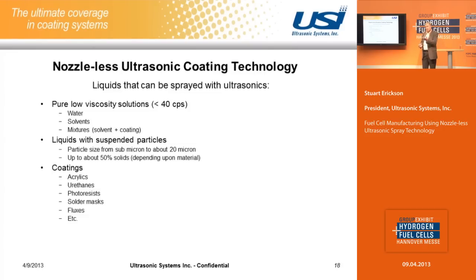The ultrasonic head just sees the carrier solvent, and the particles are entrained in each drop that's formed with the ultrasonic spray. So, as I mentioned before, depending on the type of material, we can spray materials with up to 50% solids loading in the carrier solvent. And that includes materials like ceramic slurries, it can be silver inks, it can be aluminum, different types of materials can be sprayed up to that level. And then just general coatings like urethanes and acrylics, photoresist, solder masks, fluxes, etc. can be sprayed with ultrasonic technology.